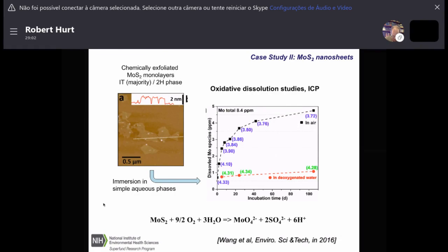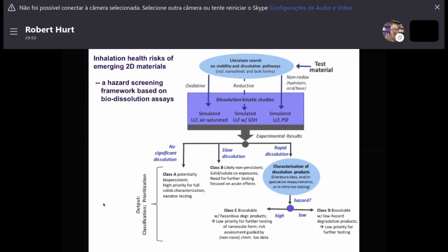We have a third type of case study, which I can't talk about today because we have unpublished data, but some 2D materials are stable in water. They're stable to oxygen, but they are unstable in the presence of biological reducing agents. So the body has antioxidants, glutathione, cysteine, ascorbic acid, a variety of compounds known to neutralize free radicals. Those are chemical reducing agents. And when these materials see those chemical reducing agents, which they don't normally do in their applications or their handling, but after exposure to human beings they will, there's another class of materials that become unstable and dissolve under reductive conditions. And so this has led us to develop and propose this framework,